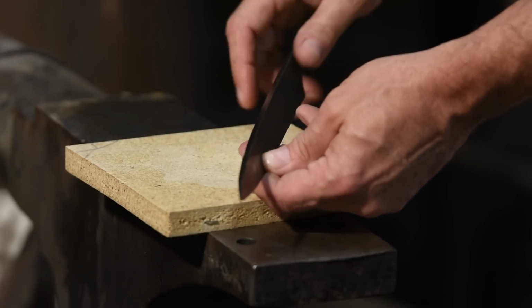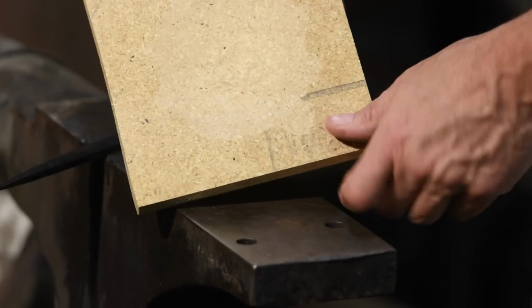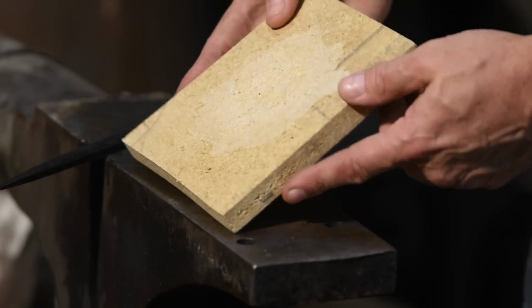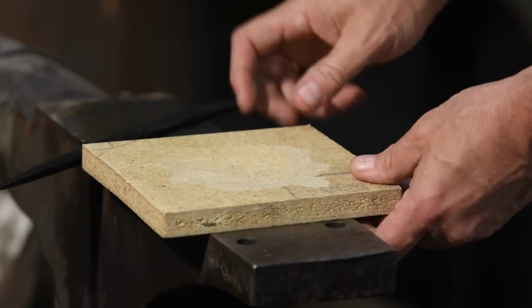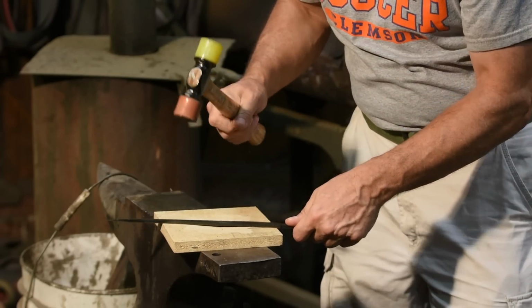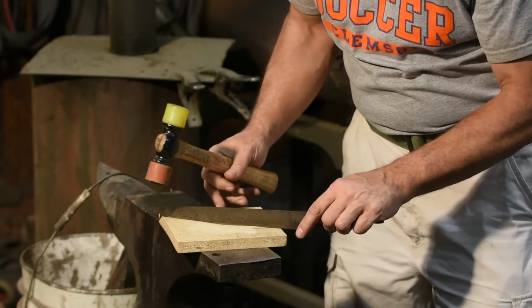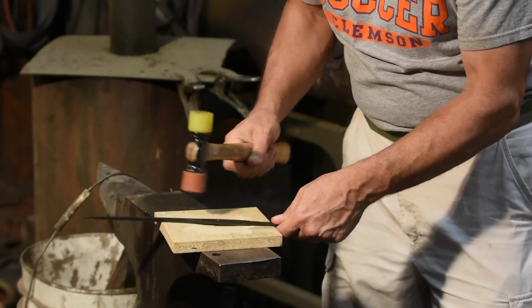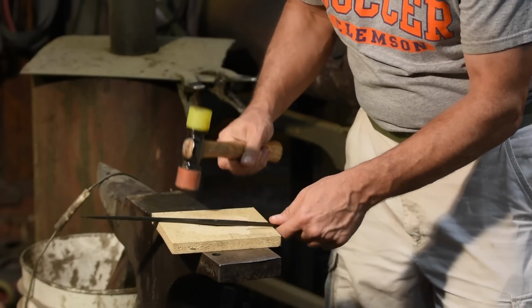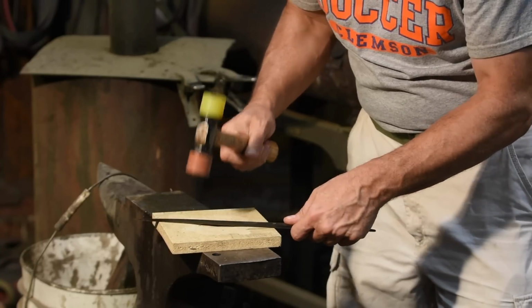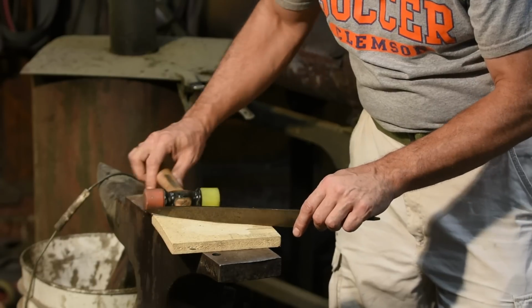First, I dished out a piece of scrap fiberboard with a large contact wheel on my grinder. It's just around 1/8 of an inch of depression, maybe a hair more. Then I gently use a mallet to beat the blade straight. If you've ever straightened Western style knives, which verges from difficult to impossible depending on how they were heat treated, this operation is so pleasant and easy. Just tap gently, keep checking patiently, and eventually you'll get everything nice and flat.